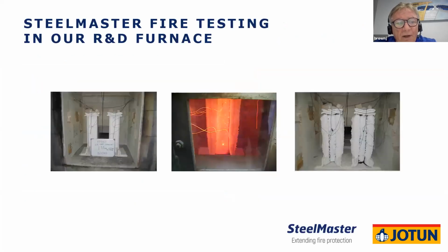If you look on the far left-hand side, this is coated steel that's put into the furnace. The middle photo is the furnace in action. You can see the bright red wires. These are thermocouples which are measuring the steel temperature, and the one on the right-hand side that's hanging down is measuring the furnace temperature. And then when the fire test is completed, on the far right side, you can see the two columns where the paint has intumesced and insulated the steel for a given period of time.